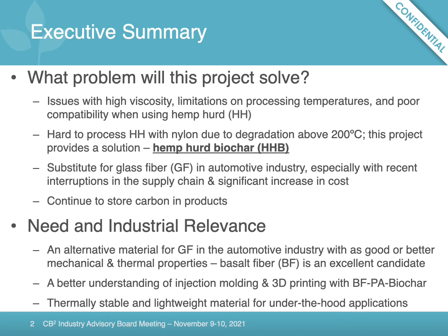But by producing hemp-hurd biochar that we are proposing in this project, we could start addressing the issue of processing at much higher temperatures, about 200 degrees centigrade, and not degrade the biomass. This project would also offer basalt fiber as a substitute for glass fiber for the automotive industry that is seeking other alternative materials, especially with recent interruptions in the supply chain and significant increase in cost. This project will also show how to continue to store carbon in products through use of hemp-hurd biochar.